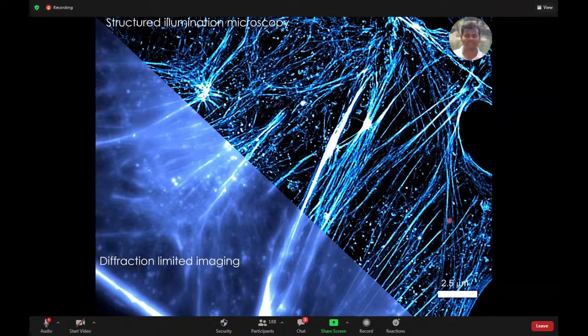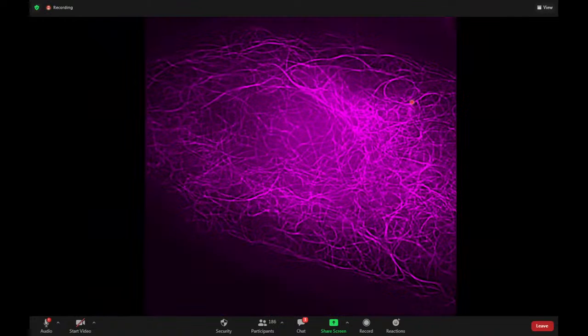So similar thing, as you can see here, this is recorded in our lab. As you can see on the lower side, this is a standard diffraction limited image, which has a resolution of 200 nanometers. But if you apply this sort of structured illumination setup, you will be able to very clearly image and resolve the molecules. So the resolution of these molecules would be around 120 or 100 nanometers, so around a two-fold increase in resolution.